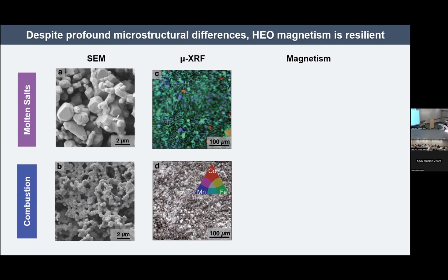And then we see that there are these small regions in blue and red where there's an excess of either manganese or cobalt, and a region here that's kind of yellow, meaning that it's manganese deficient. So that molten salt sample on a micron length scale, each pixel here is about 4 microns, is massively inhomogeneous. It's extremely chemically inhomogeneous.